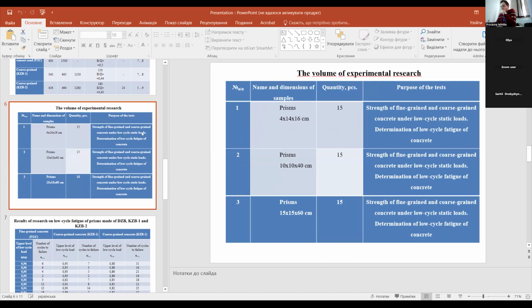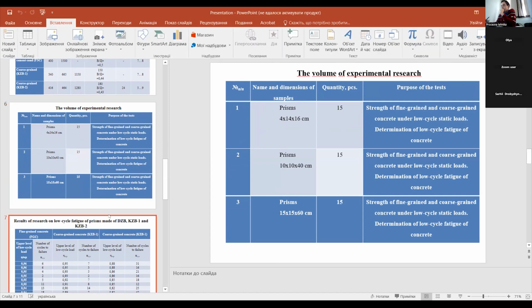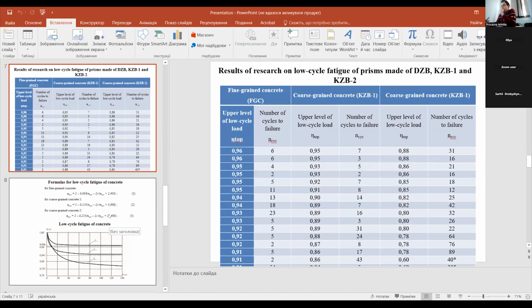Results of experimental research. The test results of the prisms subjected to low-cycle loads are presented in the table. For describing the low-cycle fatigue of the tested concrete prisms, a fractional linear function in the form of the dependency of eta on n was adopted. From the dependencies, it is evident that at their limiting values, they acquire physical meaning. The values of eta limit, 0.906, 0.841, and 0.747, correspond to the low-cycle fatigue limits for their respective types of concrete.